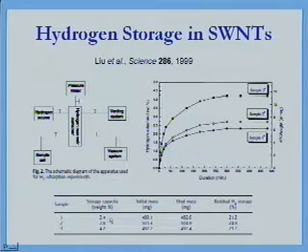And what you see is a weight storage capacity of about 3% of each carbon. The other important parameter is the residual H2 storage, which means that after you try to remove the hydrogen, the remaining hydrogen which stays inside. So you can leach out almost 70% of the hydrogen which you initially stored in the nanotubes. It is assumed that this process will be useful for fuel cells and different processes like that.